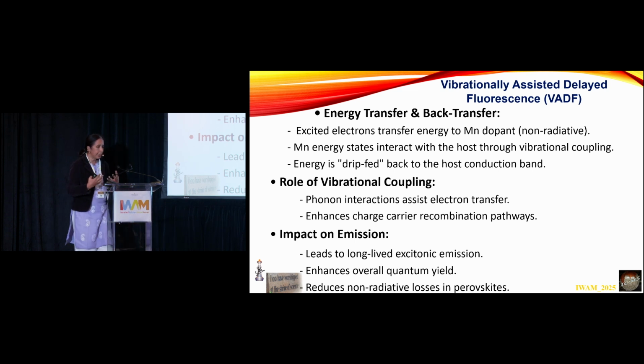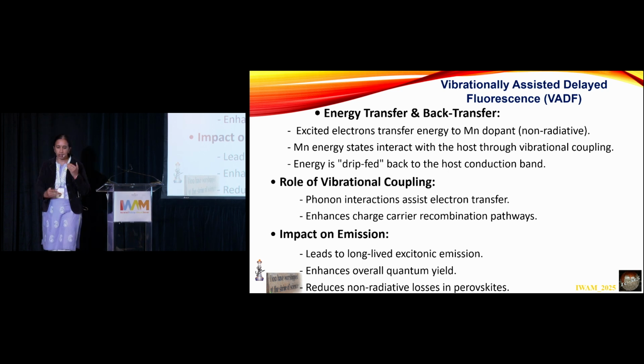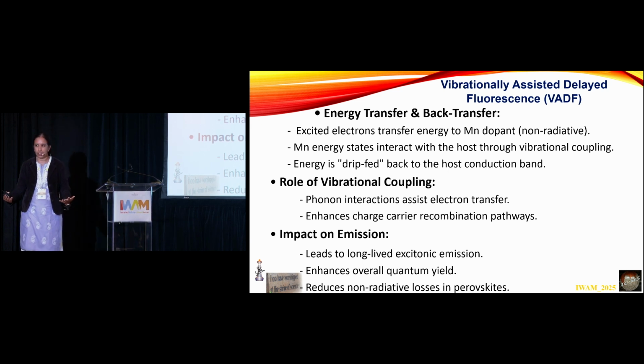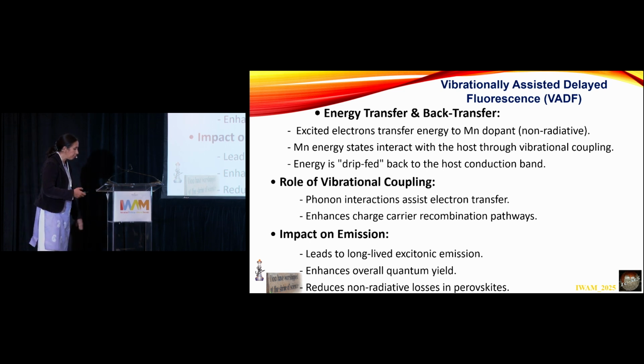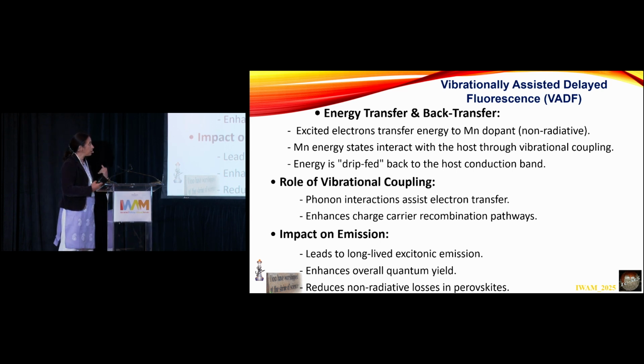So this led us to the point that probably we have vibrationally assisted delayed fluorescence, along the lines of thermally assisted delayed fluorescence, but a little different from it. I'll come to that in later slides. So what do I mean by vibrationally assisted delayed fluorescence? It's basically an energy transfer and a back transfer. You have an excited electron that transfers energy non-radiatively to the manganese dopant, and the manganese energy states interact with the host through vibrational coupling, and finally the energy is fed back to the conduction band.